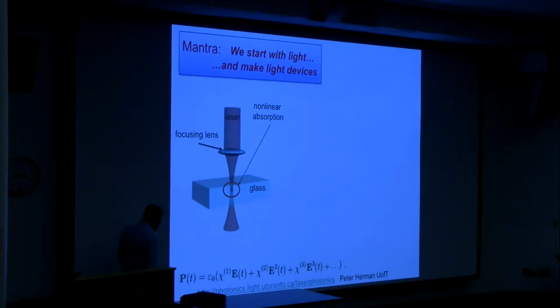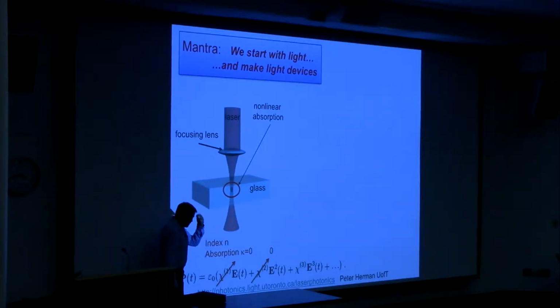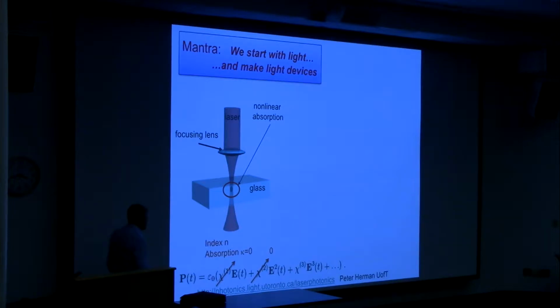If we want to use laser light and modify glass internally or on the surface, we have to remember we're starting with an absorbing material. So let me throw up an equation which talks about the polarizability of a material. How far does the electron shift relative to the nucleus of an atom or in a molecule, driven by the electric field. And so chi tells us the response of different materials. And generally in here, chi has a real part and imaginary parts which are associated with the refractive index, which we would use every day in Snell's law, and an absorption, which is zero by definition of a transparent material. So when you're presenting light to this material, all you can do is refract it, but you cannot absorb it by this linear process. So how do we get around turning on absorption?